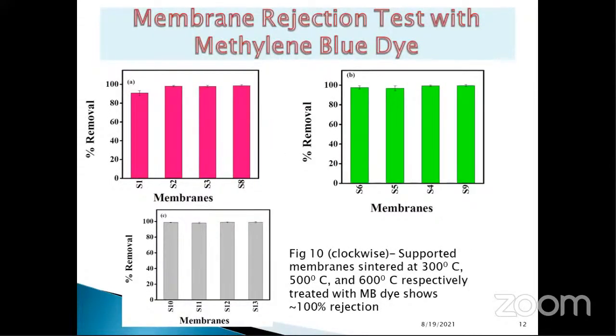We did the membrane rejection test with methylene blue dye. As we can see over here, in the membrane rejection test, most of the membranes are giving around 100% rejection at 300, 500, and 600 degrees centigrade. And this is because of the presence of the anatase phase, which has degraded the MB dye.